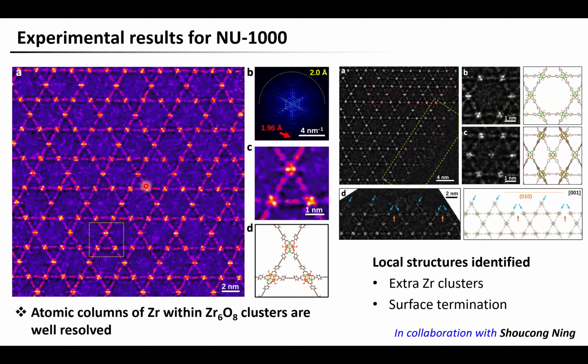And the reconstruction for the other MOF, NU-1000, ends up with an even higher resolution. With this resolution, we can resolve the neighboring zirconium atoms within the metal clusters. And we can also identify some interesting structural features in this material. For example, in this area, we see that there are actual clusters in the channels that are supposed to be empty channels. And on the surface of the crystal, we can identify the surface termination modes. We found that this crystal surface is exclusively terminated by the triangular channels rather than the hexagonal channels.